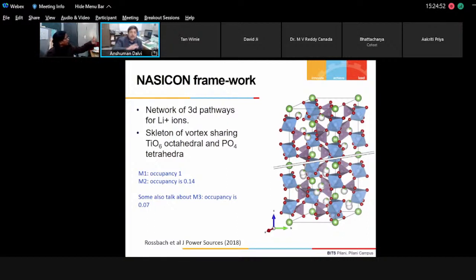You cannot see the movement of lithium ions along M1, but you can see the movement along M2 and M3, and by some doping, we can use these M1's lithium ions to travel through the M2 and M3 sites, and therefore there is a huge conductivity in NASICONs. A very similar process is there for the garnets also, where you have defects, and through those defects ionic motion